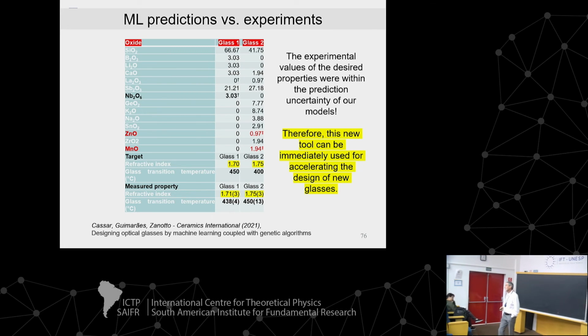So I imagine that the refractive index and glass transition temperature, let me call this a two-dimensional vector, is a function of 39 variables, namely the 39 composition elements. What does this manifold look like? As in, if you change, let's say, only one composition slightly, is it very steep, or does a slight change make a very large change in this vector? It's a good question. We never tried to plot this, but I can give you my feeling on this. These two properties are very sensitive to composition. Other properties are not very sensitive, like the elastic modulus. But the refractive index and TG are sensitive to minor changes in composition. So I think it would be steep, but I never plotted it.